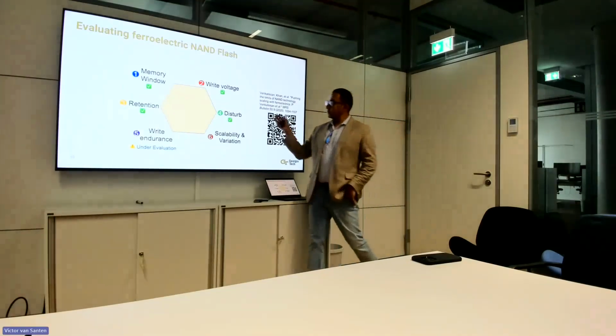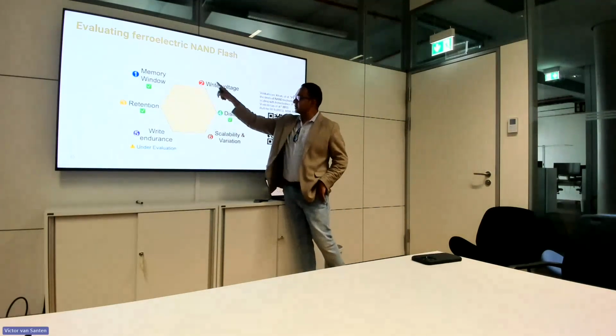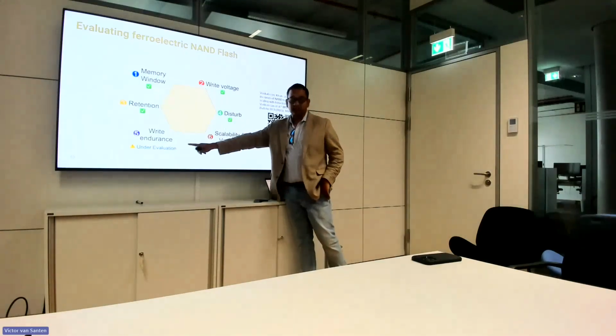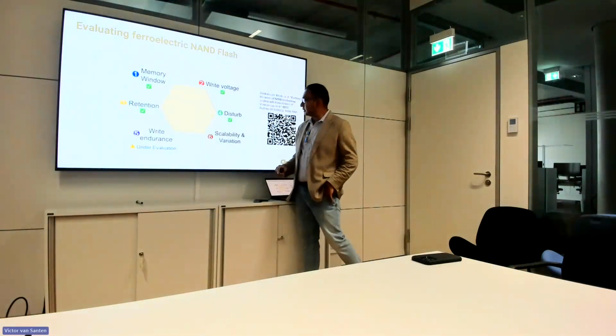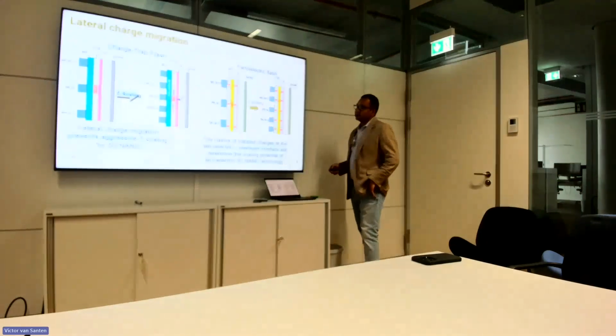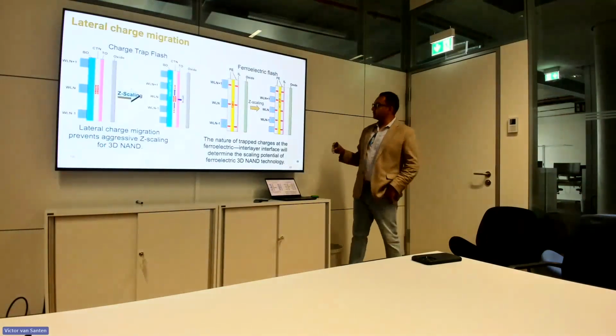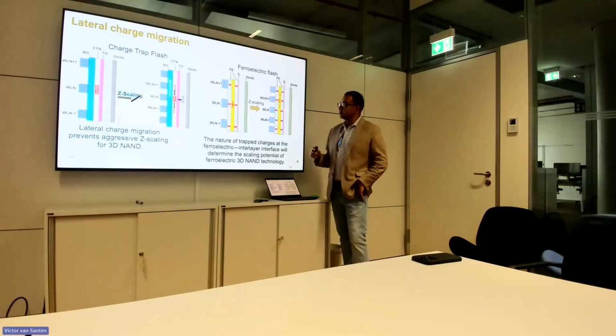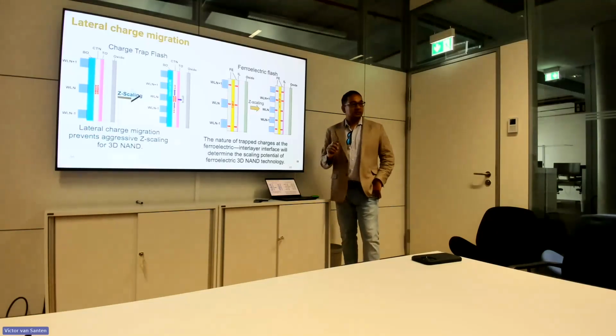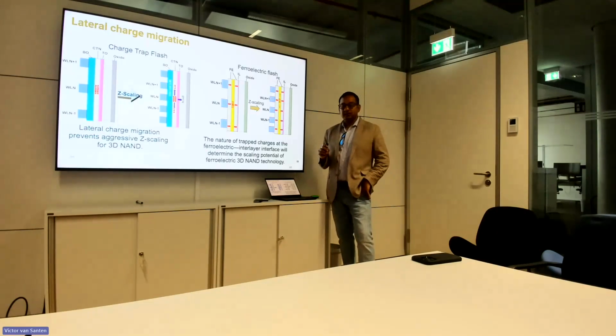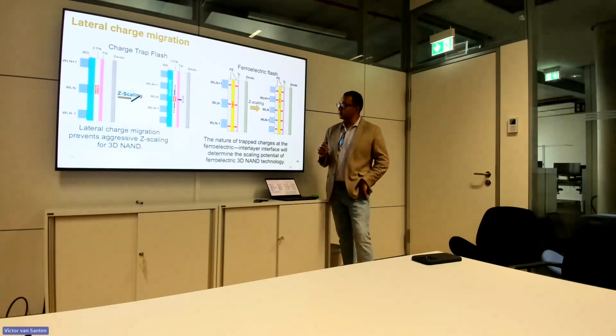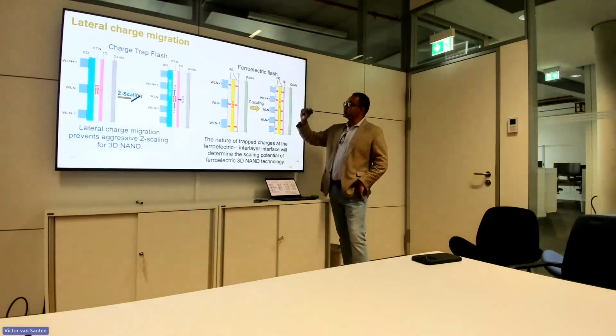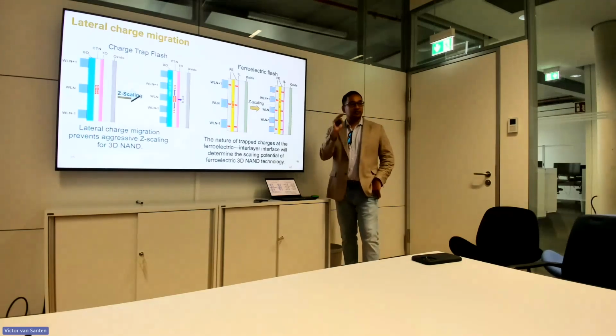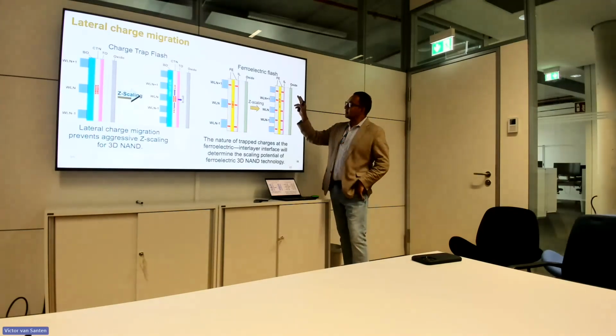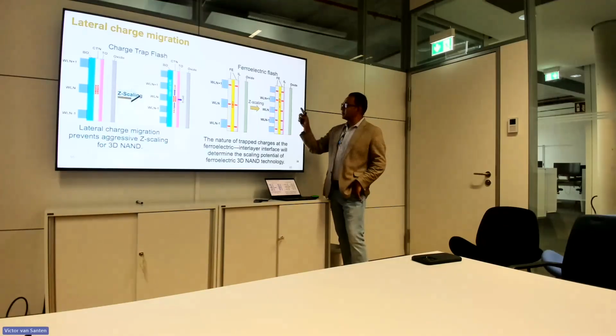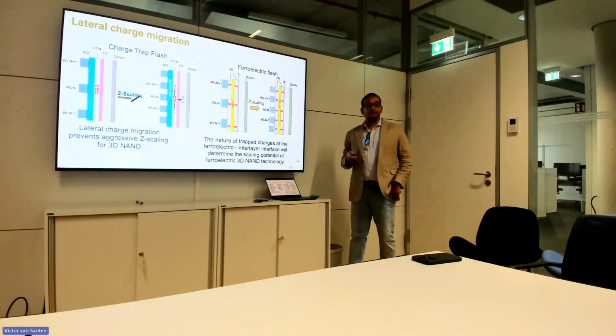So overall in the six-metric matrix, these three are more or less under control, I think. Right, endurance is something that we are working on. And scalability and variation is something that we already discussed. Our initial idea was that we don't use trap charges, but rather ferroelectric bound charge. It should be better, but we are actually using trap charge to increase the memory window. But we think that the lateral charge migration will be much less because these are basically interface traps.